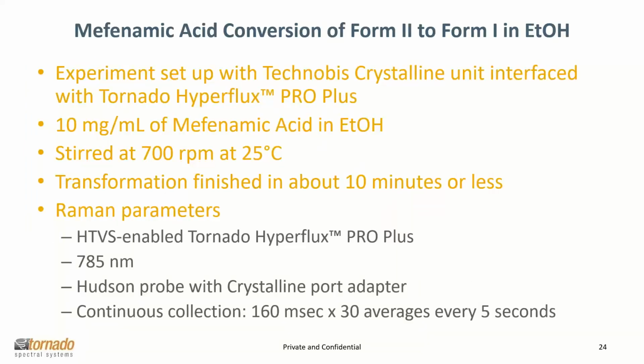And there were two target molecules that were examined with the studies that we did. One, as Thomas mentioned before, was the mefenamic acid, where we were following the conversion of form 2 to form 1 in ethanol. So you can see the experimental conditions here. And as Thomas mentioned, the transformation in this particular case was finished in about 10 minutes or less. And so, again, quicker measurements, high quality measurements, the faster the better in cases like this, to be able to follow the process, detect the endpoints, and understand the process in the best way possible.